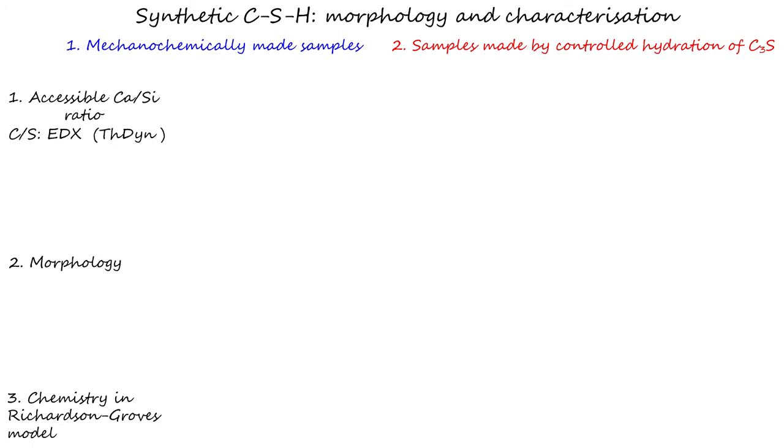It can be summarized like this. CSH is known to be like the mineral tobermorite, but in Portland cement, the calcium to silicon ratio is much higher than in tobermorite. To compensate for this fact, the tobermorite structure is modified by removal of silicon. When this is no longer possible, additional building blocks of the mineral jennite are introduced to push the calcium to silicon ratio even higher. On the Nanocem webpage below this video, we provide some links to publications of Ian Richardson about the Richardson-Groves model.